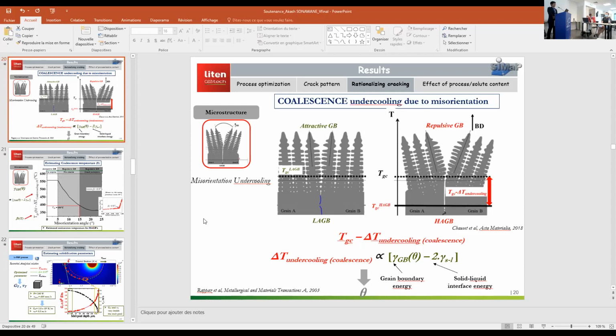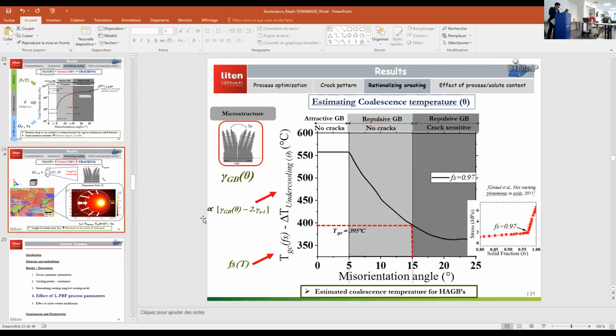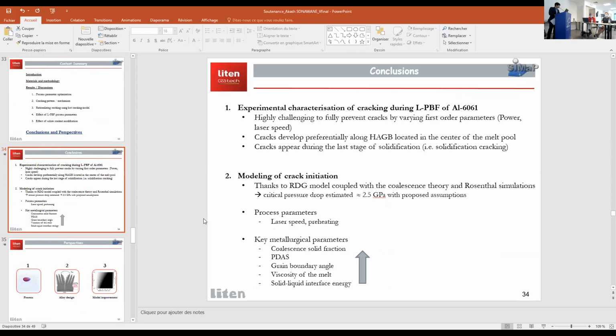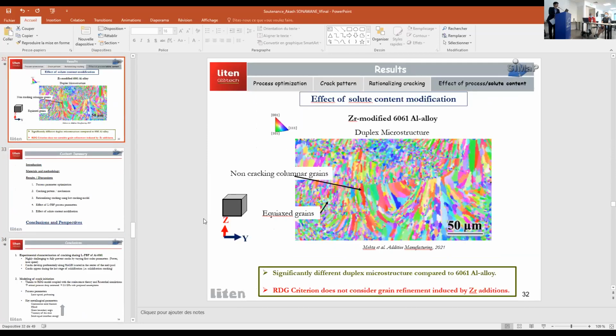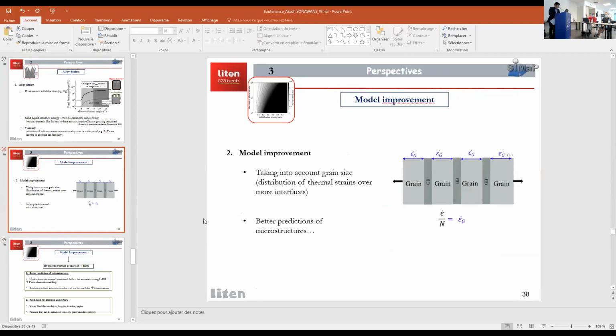The other aspect is grain structure. True. And if you go to slide 32, maybe you mentioned the strain localization. When you have epsilon dot divided by n, maybe further down. Yes, strain localization. So one way to reduce hot cracking, and it's well known, is to have a finer microstructure. True. Because each liquid film that might survive will support less strain. So in your process in L-PBF, could you imagine to have a finer microstructure?